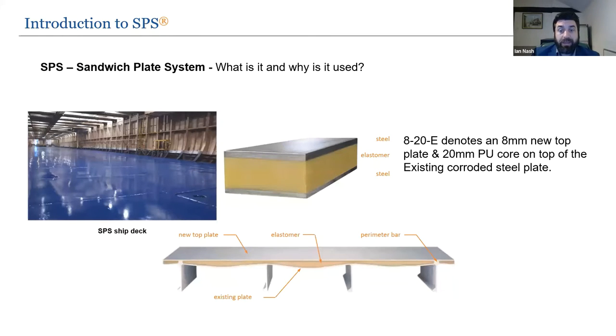There are many additional benefits: excellent energy absorption since the polyurethane is a solid elastomer, noise and vibration deadening, protection against impact, blast and ballistics and fire, along with competitive economics. Studies showed that for a typical marine reinstatement SPS is four times faster, and for offshore hull plating work on an FPSO or semi-submersible below the waterline it's 11 times cheaper.